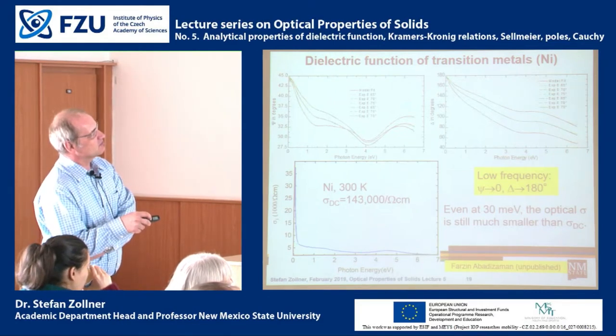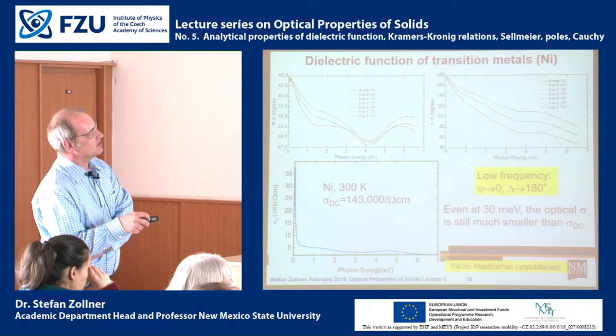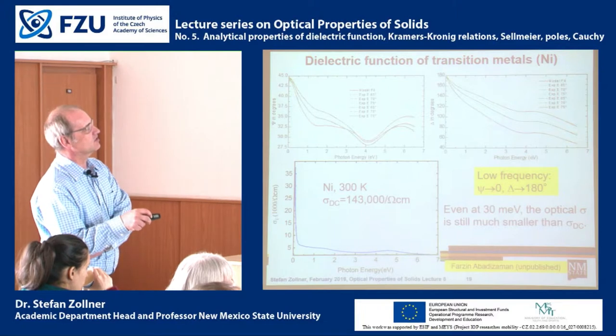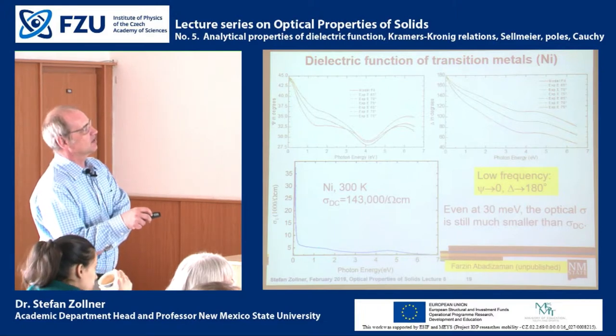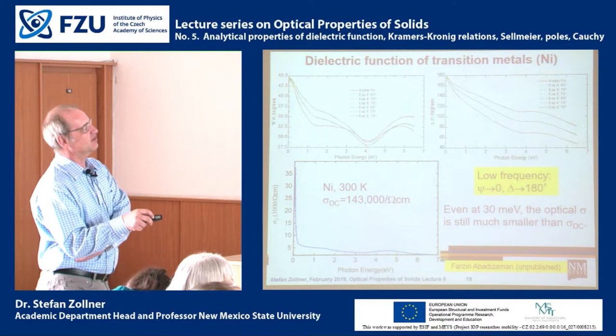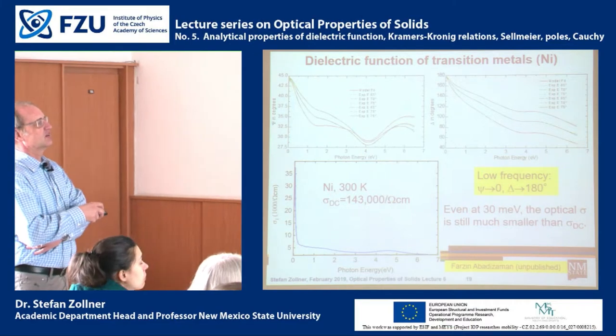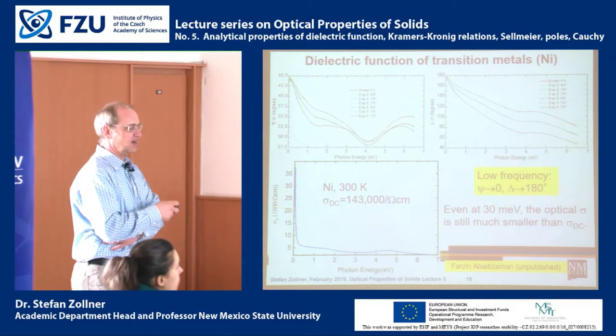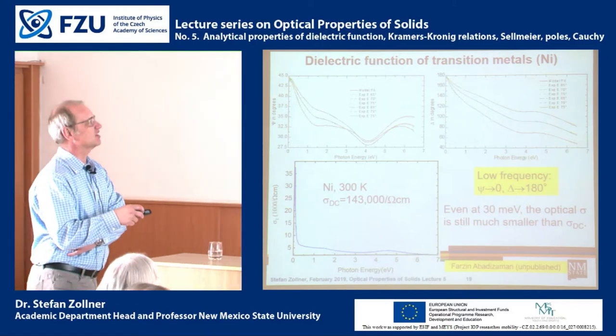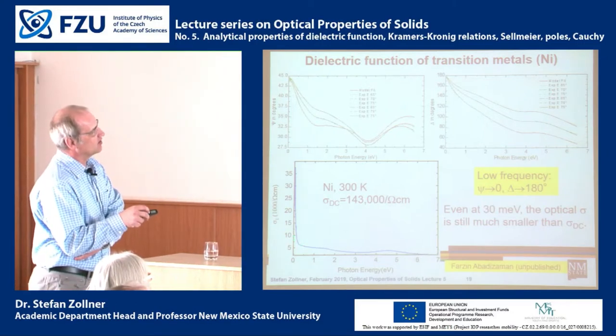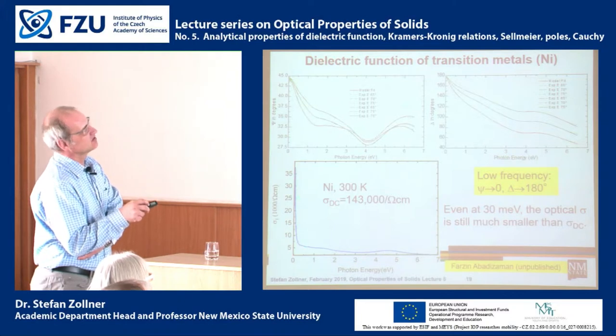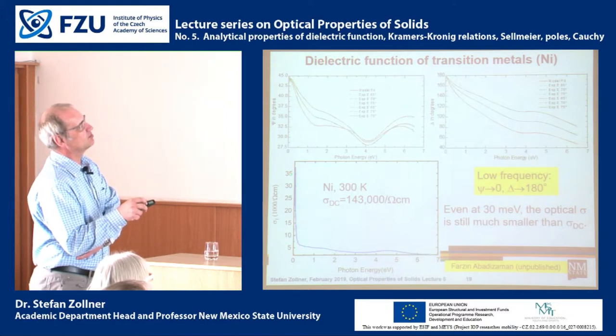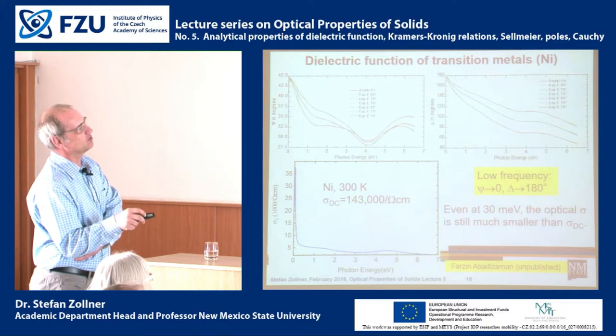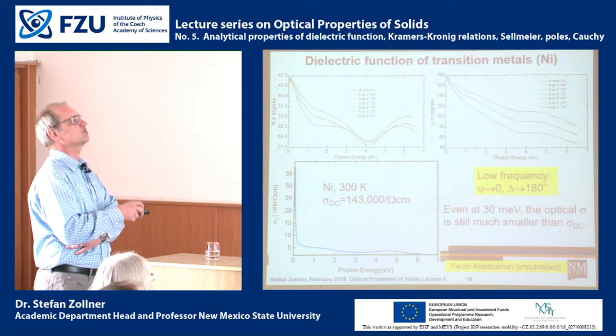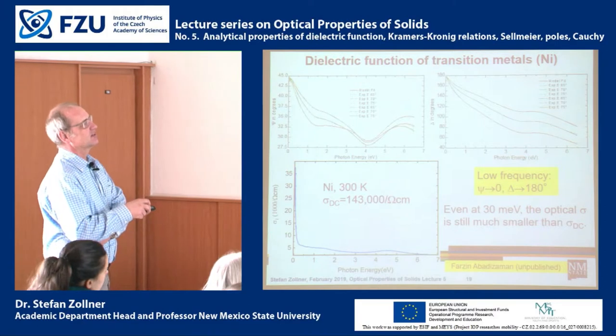And so you see that this is the optical conductivity due to interband transitions. So this is the Lorentz part, the absorption peaks at 1.5 and 4.5 electron volts. These absorption peaks are due to the oscillations of bound carriers in nickel. And then below 1.5 electron volts, the conductivity shoots up, but even at the lowest frequencies where we can measure, about 30 milli electron volts or 250 wave numbers, even here